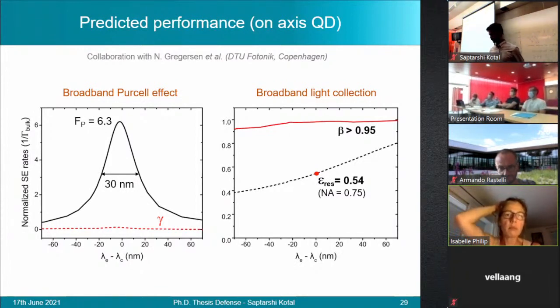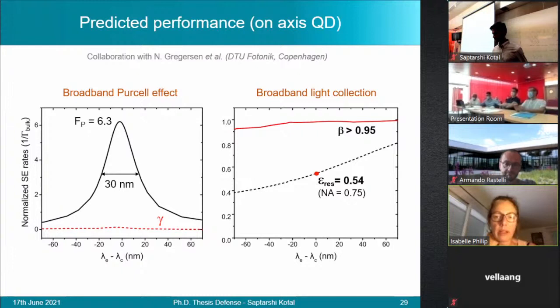Because in the case when you are on resonance, you accelerate the emission, so you have a preferential funneling inside the mode. And this is not what you see in the beta. So I have difficulty to match these two curves. How do you explain this constant beta in that case?